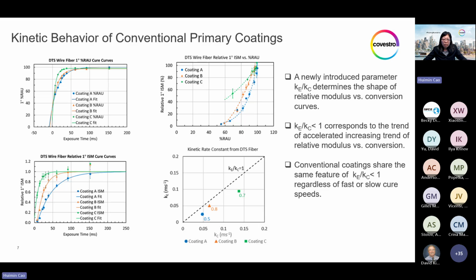In our 2020 paper, we showed three coatings, A, B, and C, from slow to fast in cure speed, not only in conversion but especially in modulus buildup. This is A, B, C from slow to fast. When plotting these into an ISM versus RAU curve, it shows A having the sharpest rise of modulus at the last stage of conversion, and C being much flatter.